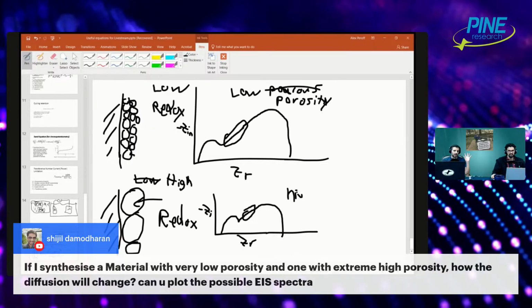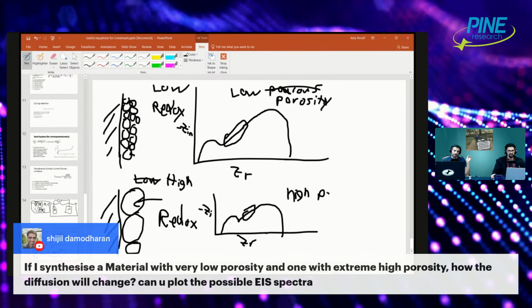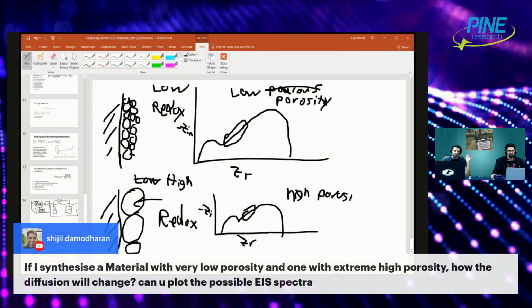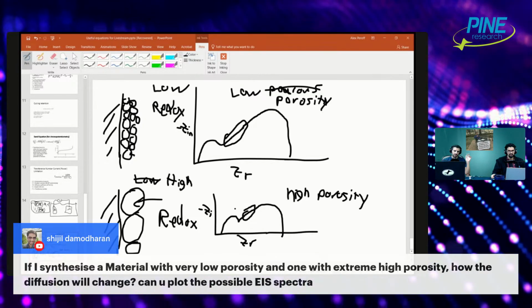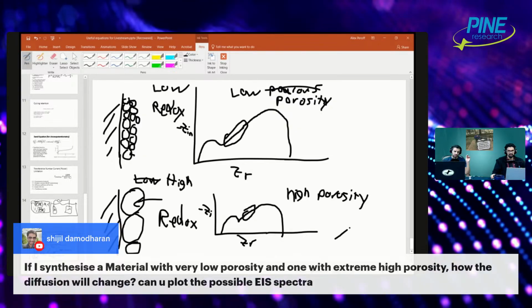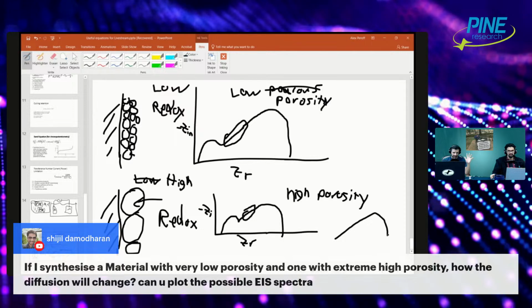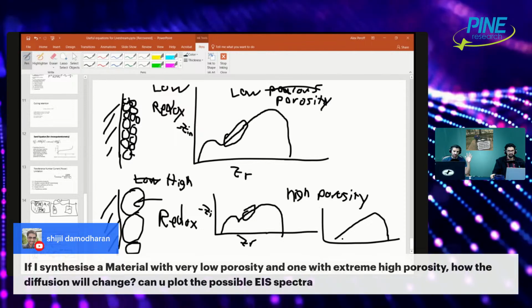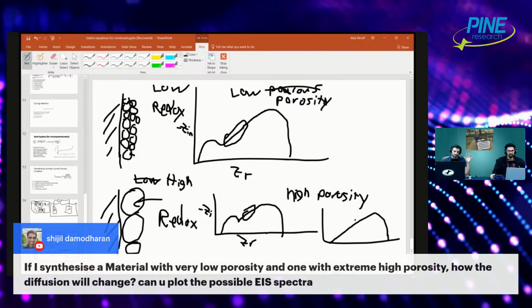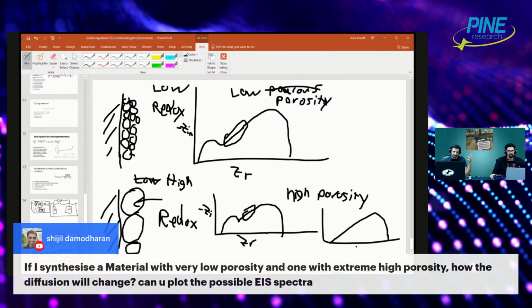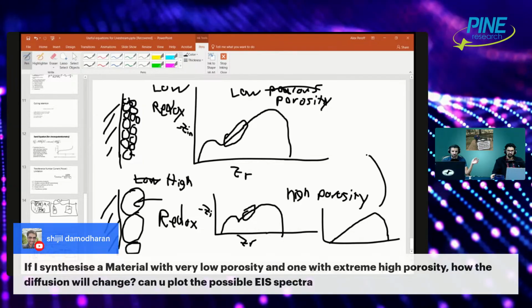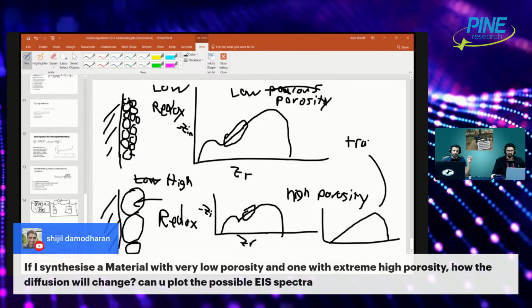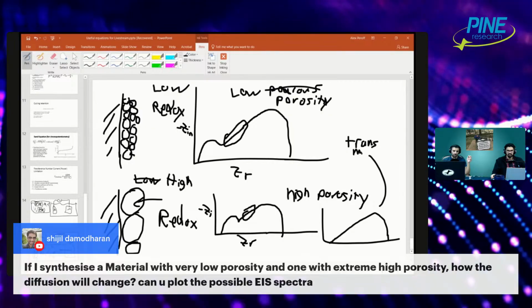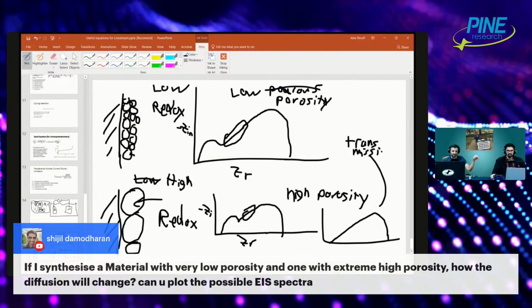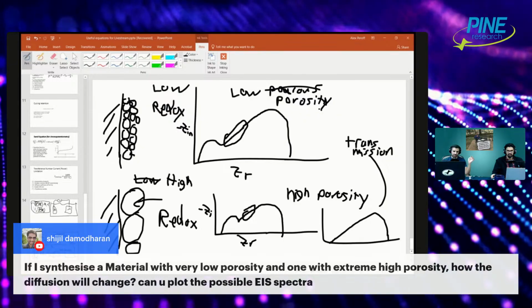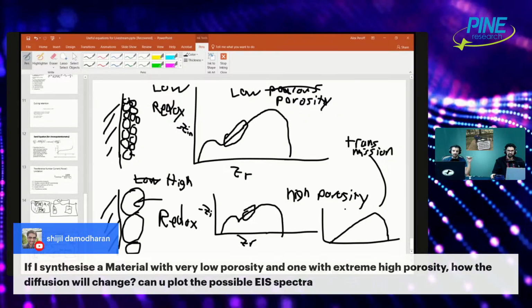Now, the only possible wrinkle here is that with porous electrodes, you sometimes get what's called a transmission line, which you could imagine looks just like what Alex is drawing here, except the first semicircle is not present. So it would just be like the Warburg short. And the length of that first section would be proportionate to the porosity, the way we described. So the top one would have a long 45-degree section, and the bottom would have a very short 45-degree section before it curls, or just a lower impedance overall, is my guess. That's our guess.